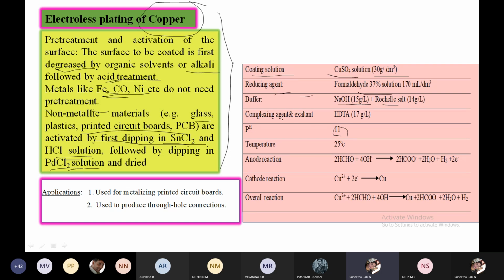So what is the complexing agent or chelating agent we are adding? We are adding EDTA, that is 17 grams per liter. Based on this concentration, you can add EDTA. So these are the reagents for preparation of bath solution. Coating solution is copper sulfate, reducing agent is formaldehyde, buffer is NaOH or Rochelle salt, complexing agent or chelating agent is EDTA, pH is to be maintained at 11 and the temperature maintained is 25 degrees Celsius.